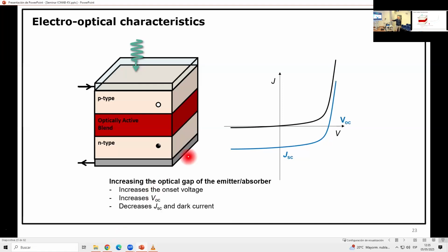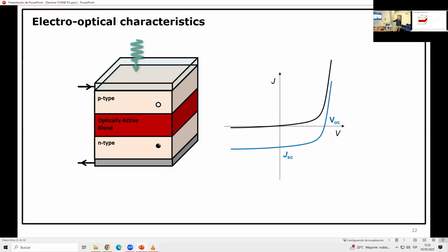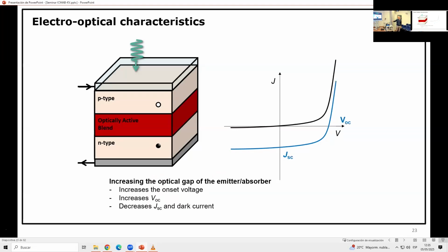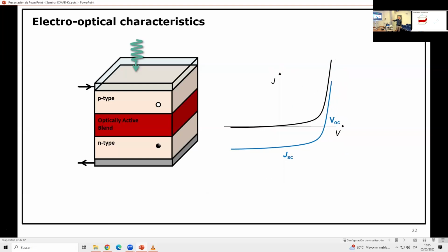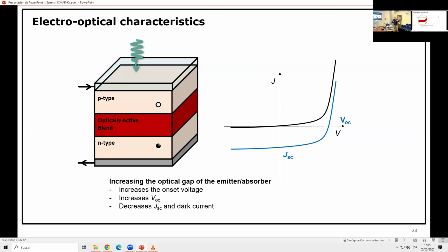So if you increase, for example, the optical gap of the emitter or absorber, suppose you start from a red LED and you make it a blue LED. For blue light, you need more energy, so voltage times current will be higher for blue light. So the IV curve for a blue LED will always be shifted to higher voltages than the one for a red LED. And for a solar cell, it's similar. For a solar cell with a higher gap, which absorbs less light, in the dark, that IV curve will go up at higher voltages.